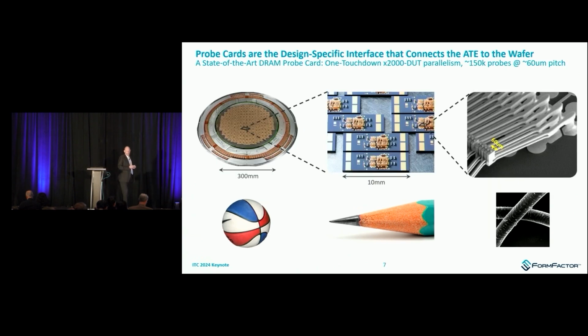Here's DRAM state of the art. A very different kind of approach, but still using the same fundamental technology building blocks. In DRAM, rather than testing 16 die at once, you're testing the whole wafer at once. Every die on the wafer tested in parallel. One, because you can do it. I was on a panel with Phil Bird yesterday, and he talked about, from Micron, DRAM having pretty shallow vector depth. Well, here's one of the advantages that gives you compared to SoC. You can test every die on the wafer at once, and that has wonderful cost of ownership.